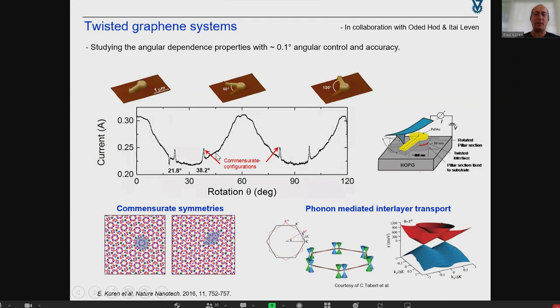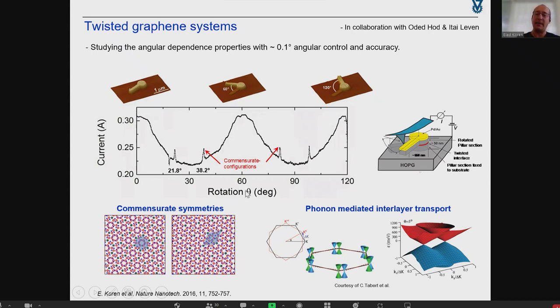We used this to measure how the interlayer conductivity changes as a function of angular mismatch — measuring the current as we continuously rotate the structures — which allows us to get really unprecedented angular resolution. This allowed us to see for the first time very abrupt and narrow conductivity peaks. The mild bathtub-like shape modulation is induced by phonon-mediated interlayer coupling: when you rotate the flake in real space there is also rotation in k-space, creating momentum mismatch that a specific phonon branch can mediate.